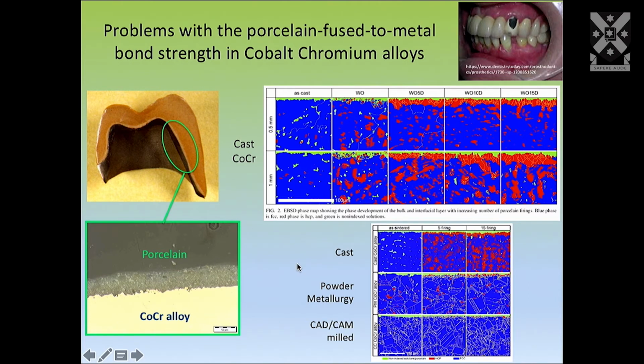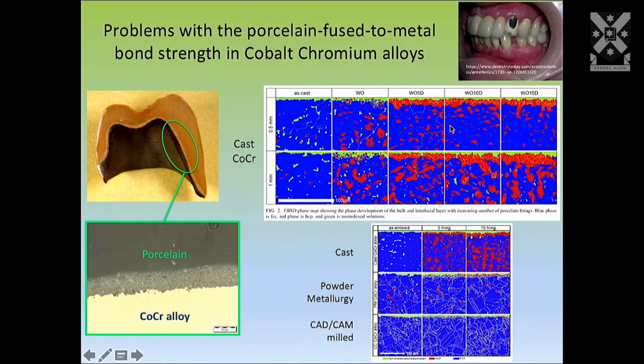And we then fired it and fired it and fired it, simulating when the crown is being first firing, second firing, etc. And we found that the phases were changing, and it was starting to form this phase at the top, which had different mechanical properties and was very rigid. So when the bilayer of the porcelain and the metal are contracting together, it was setting up these residual stresses. And this was quite serious.